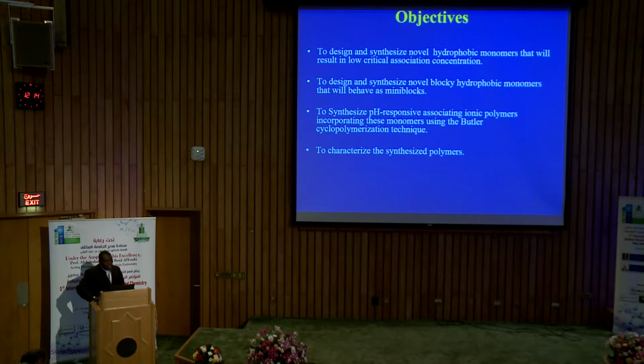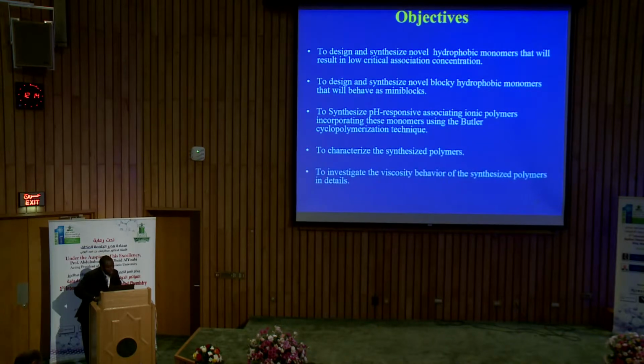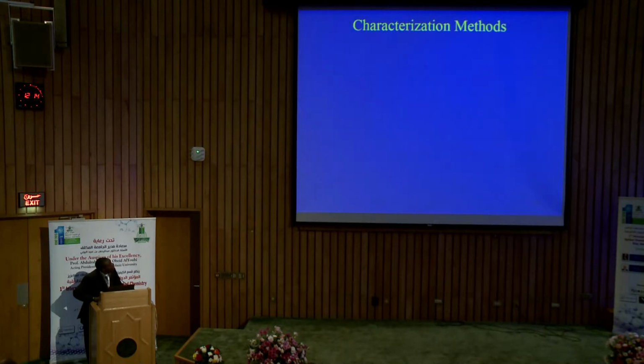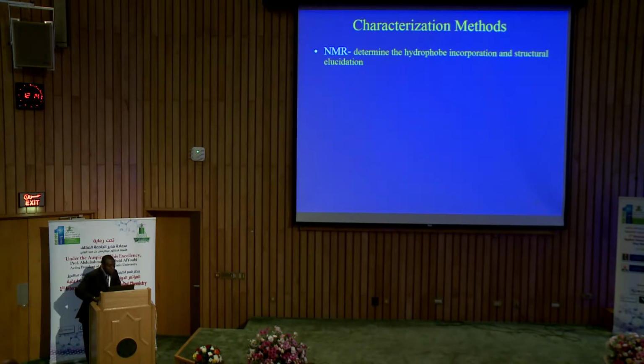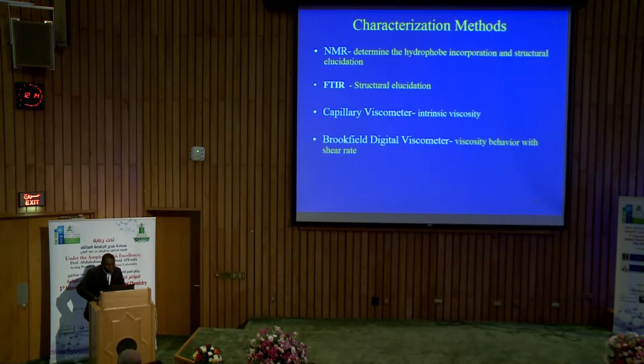And then we also characterize these polymers using different characterization techniques, and we investigate the viscosity behavior of these particular polymers. We use the following characterization methods: NMR mainly to determine the hydrophobic content and also for structural elucidation. We also use FTIR for structural elucidation, capillary viscometry for intrinsic viscosity measurement, Brookfield for viscosity at different shear rates, and then we determine the molecular weight, Mw, the radius of gyration, and the second virial coefficient using static light scattering.